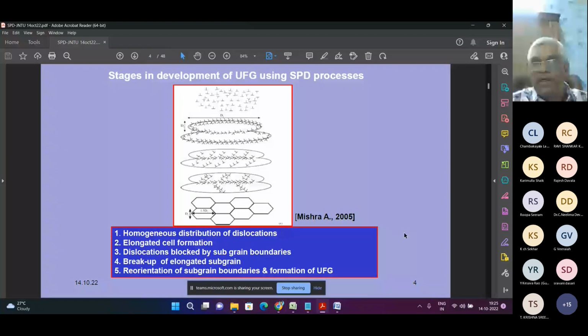Mishra A et al. published a paper in 2005 and gave a beautiful explanation of how ultrafine grain structures are formed. Before that, what we had done was grain refinement. In aluminum alloys at room temperature, when you deform or form them, you get an average grain size of something like 80 to 100 microns. But when you use titanium and boron master alloys to grain refine the aluminum, you get a 30 to 40 micron average grain size. Most people must know that you can measure this using an optical microscope.